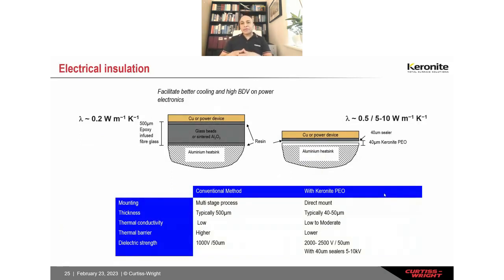Another interesting application is electrical insulation. As you can see on this one, this is an aluminium heat sink. Usually you have epoxy-infused fiberglass to achieve high breakdown strength. The problem here is very low thermal conductivity and a moderate breakdown voltage. This epoxy-infused fiberglass gives about 1,000 volts for 50 microns. With the same coating thickness of PEO, you can achieve 2,000 to 2,500 volts per 50 microns, and also a much better thermal conductivity, like 5 to 10 watts per meter per Kelvin.